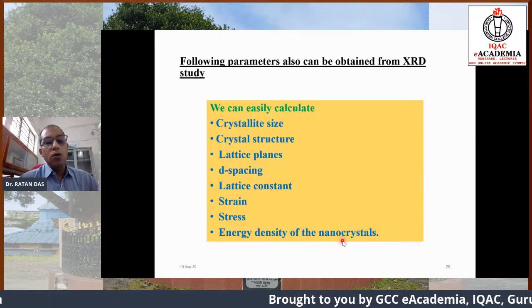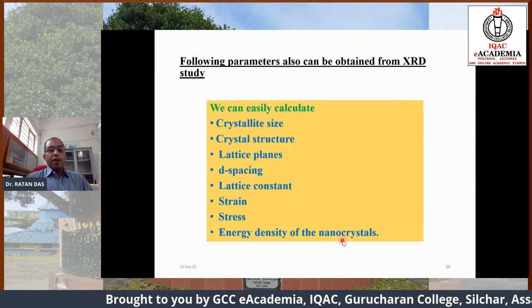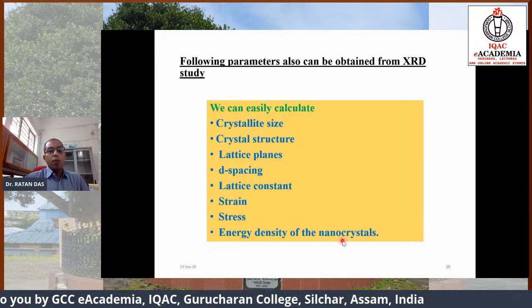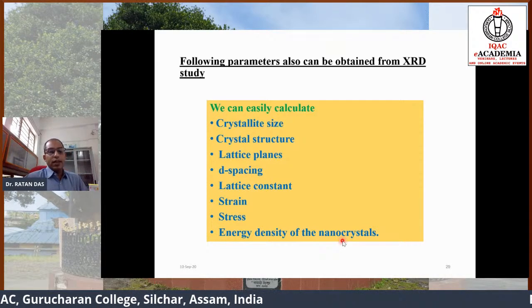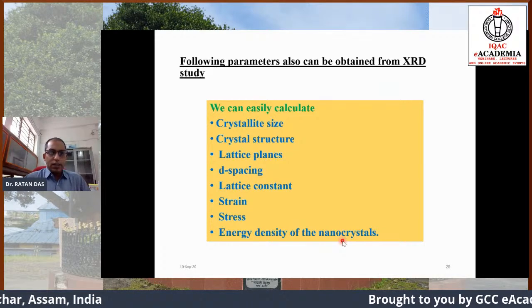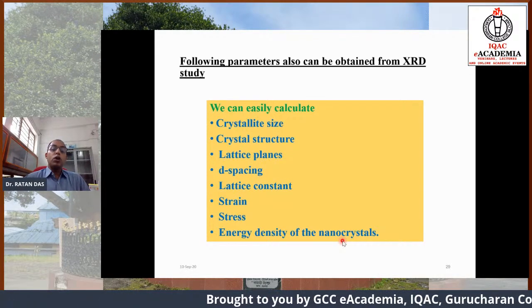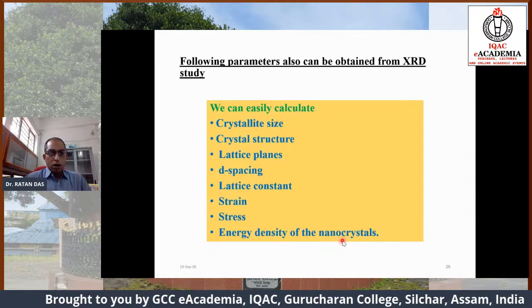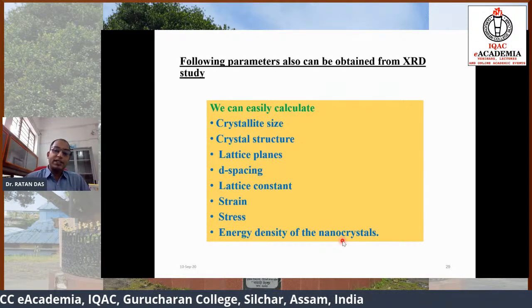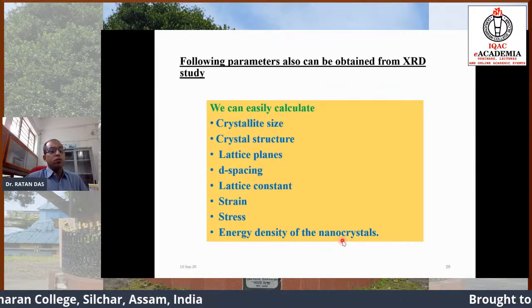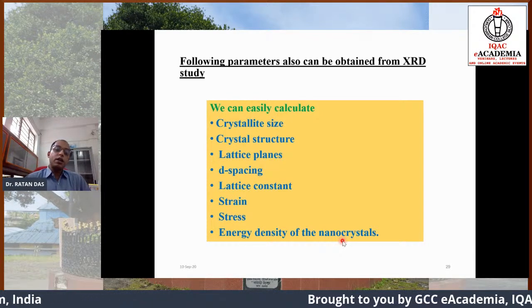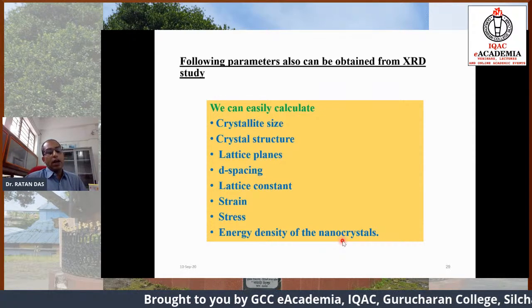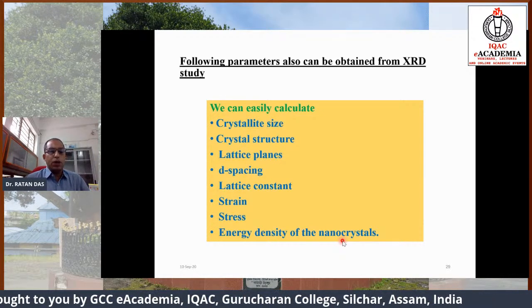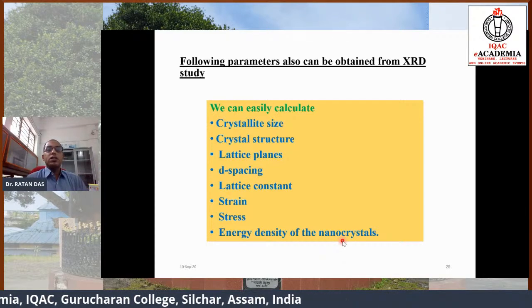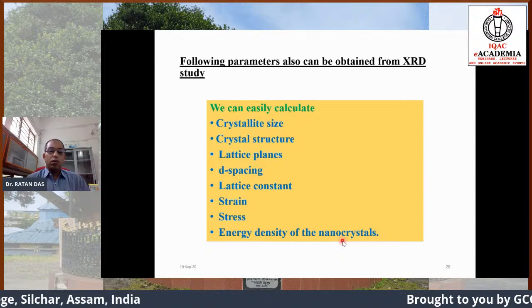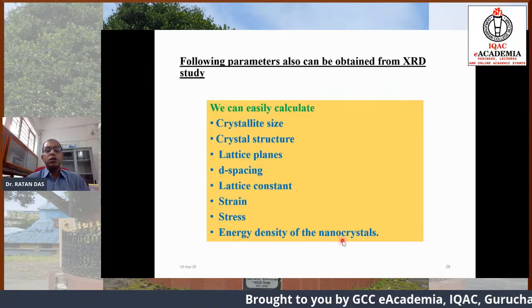Now going to the next slide, what I want to tell you is that X-ray diffraction pattern analysis is very important. Important in the sense that we may obtain the crystallite size, the crystal structure, the lattice plane, the d-spacing, the lattice constant, and strain also. Using different models we can obtain the internal stress and internal energy density that exist in the nanocrystals. All these variables we may obtain from a single X-ray diffraction pattern. That's why the X-ray diffraction pattern is very important.